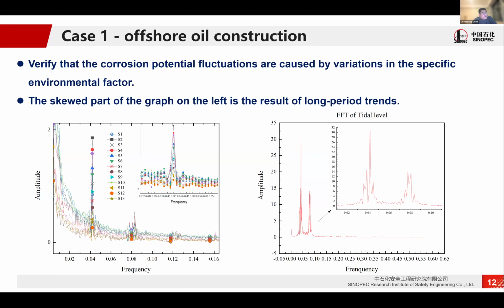In this regard, we carried out verification work. We use the Fourier transform. The Fourier transform is applied to the data of a long period open circuit potential monitoring and the periodic change of environment. It is found that the peak value of the transform has a good consistency. The skewed part of the graph on the left is the result of long period trends. The characteristic peaks after Fourier transform also verify that this fluctuation is caused by the periodic change in the environment factors.